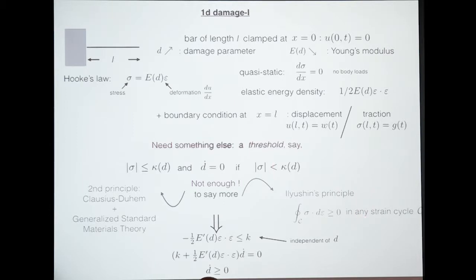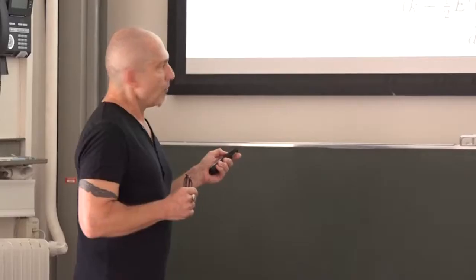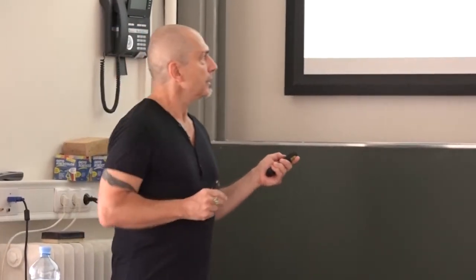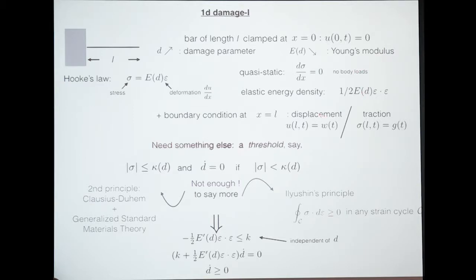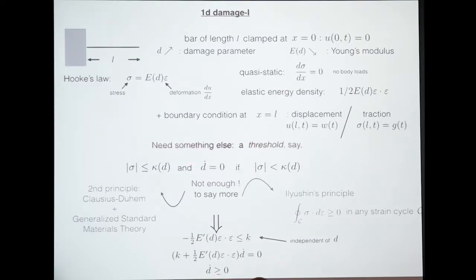On top of this, because of either this principle or that principle, you get the following things. So I assume E is a smooth function of D, that minus the derivative with respect to D of the elastic energy is less than some constant, which is not the same as that one, but very important, which is independent of it. Second, that D dot will be 0 unless you have equality here. And third, that D dot will be non-negative. So this delivers the fact that damage can only increase, and then it tells you how it increases.